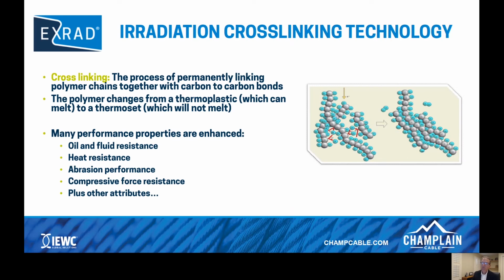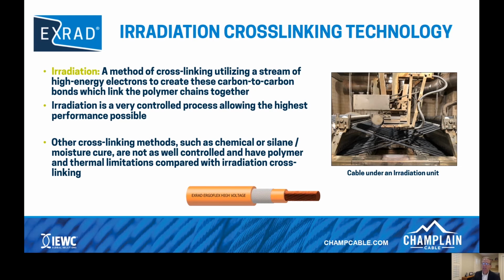So most cables that you probably work with are either cross-linked or at least a thermoset. Silicone, for example, is not cross-linked, but it is a thermoset. And polyolefins are cross-linked to become thermosets. So our method of doing this is irradiation. And this method of cross-linking utilizes a stream of high-energy electrons to create these carbon-to-carbon bonds, which link the polymer chains together. And irradiation is a very controlled process and allows the highest performance possible.